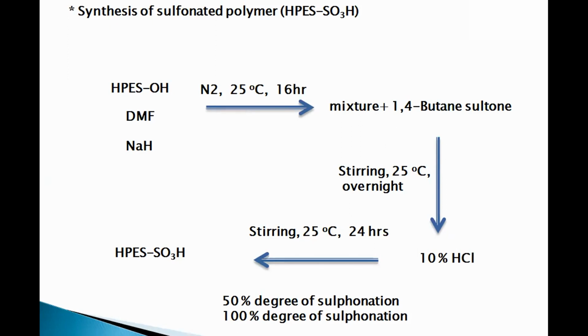And then we have to add butane sultone as a source of the sulfonic group to the mixture. This step runs under stirring at 25 degrees overnight. Then we add droplets of 10% hydrochloric acid and stir at 25 degrees for 24 hours, and produce hyperbranched ether sulfone SO3H. We prepared two types of this membrane based on the sulfonation degree, 50% and 100% degree of sulfonation.